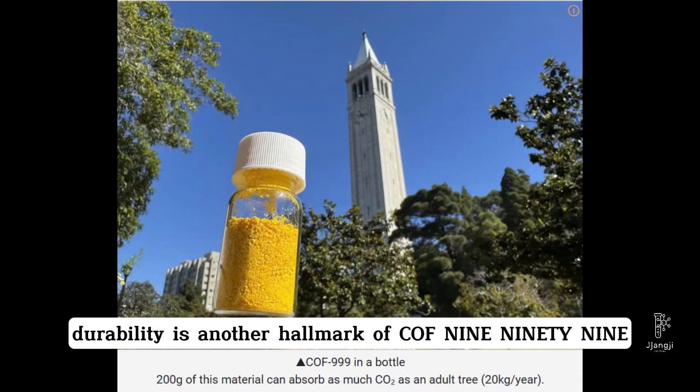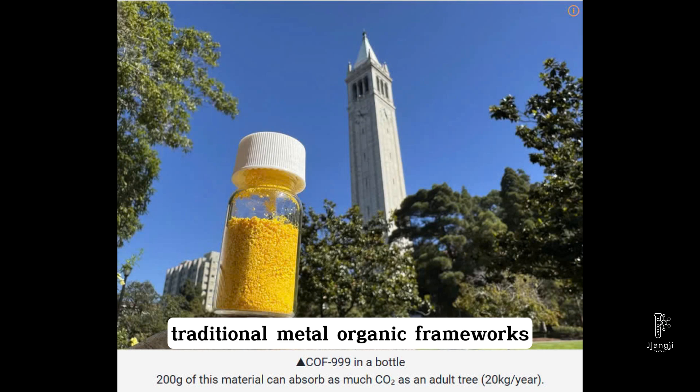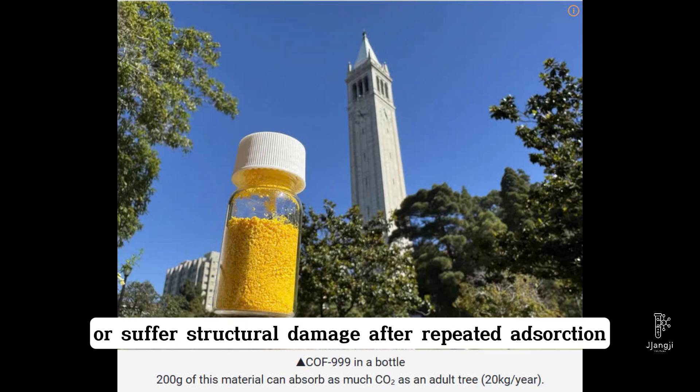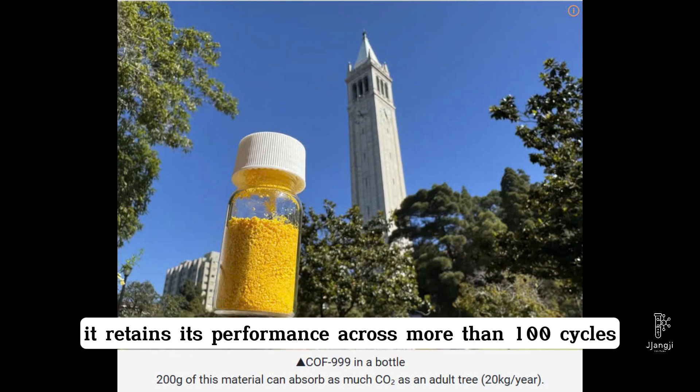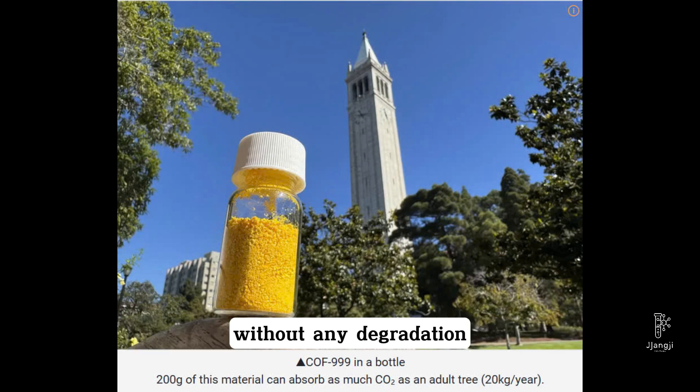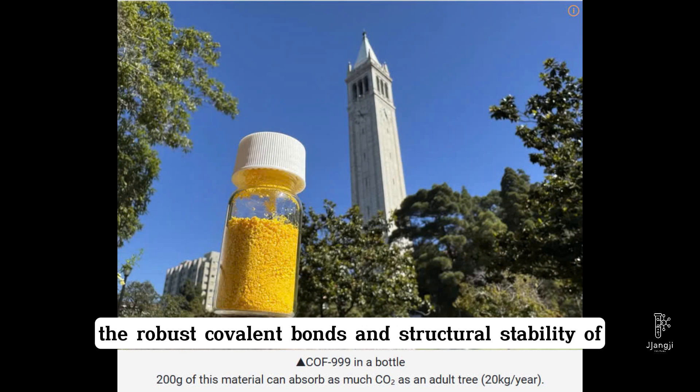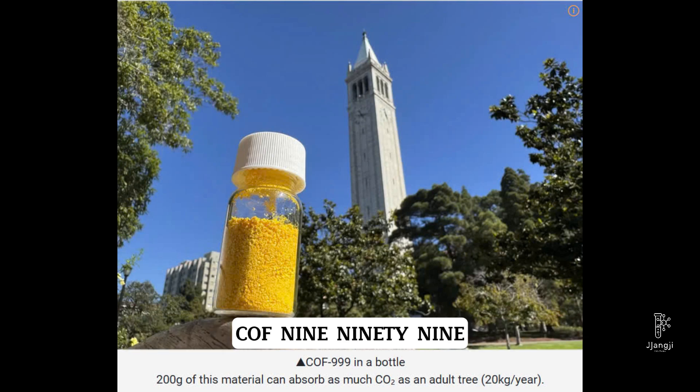Durability is another hallmark of COF-999. Traditional metal-organic frameworks (MOFs) often degrade or suffer structural damage after repeated adsorption-desorption cycles. In contrast, COF-999 has been specifically engineered to overcome these limitations. It retains its performance across more than 100 cycles without any degradation, demonstrating exceptional resilience. The robust covalent bonds and structural stability of COF-999 make it a reliable solution for long-term commercial use, further solidifying its practicality and cost effectiveness.